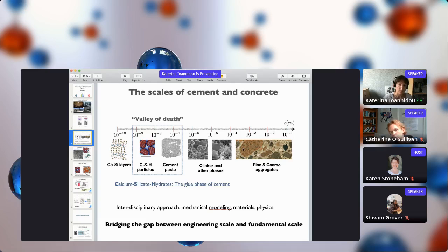If we start zooming into the cement phase of the concrete, we can see several hydration products in the scale of microns or millimeters. We have crystalline materials inside there, but the most important phase is what is called the calcium silicate hydrate, which is the glue phase of the cement. It has such a vague name because there is no specific stoichiometry for this phase of the cement. At the atomistic scale, there have been quite some simulation efforts to figure out the structure of this material at the molecular level.